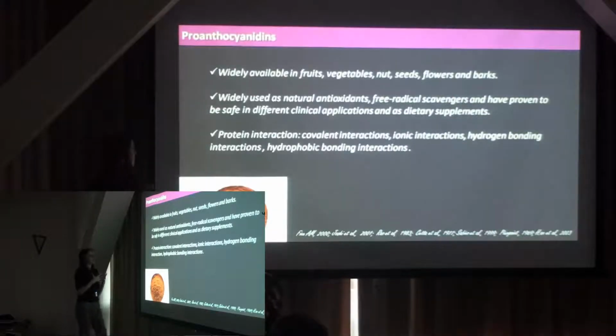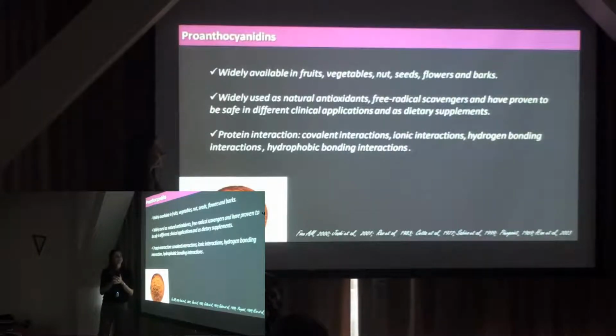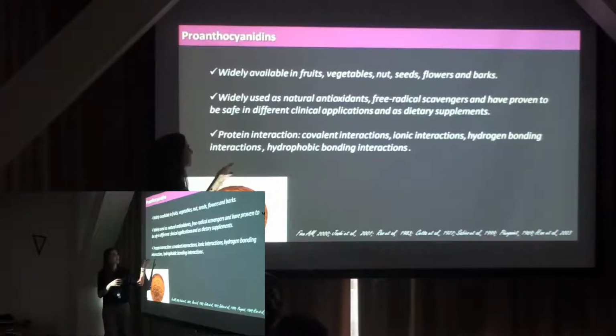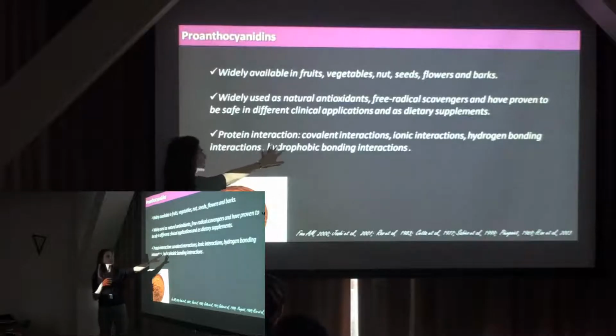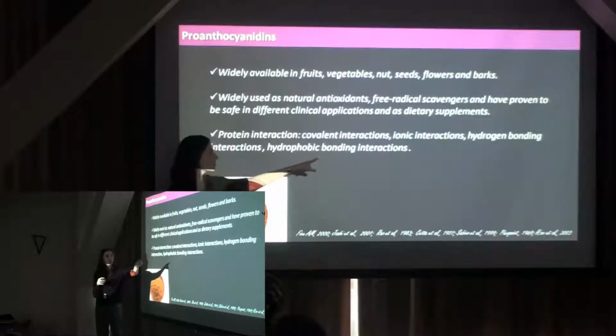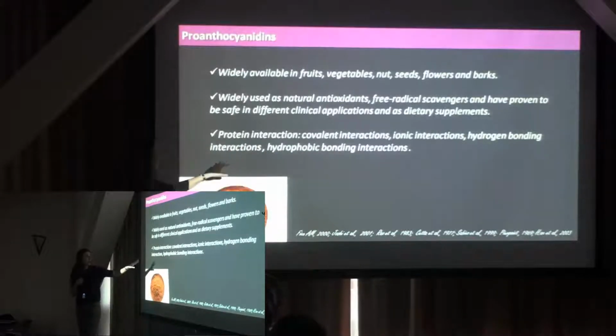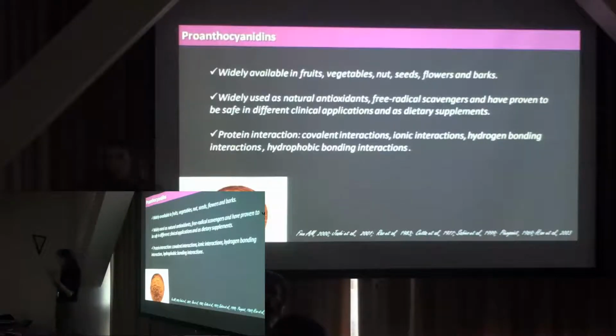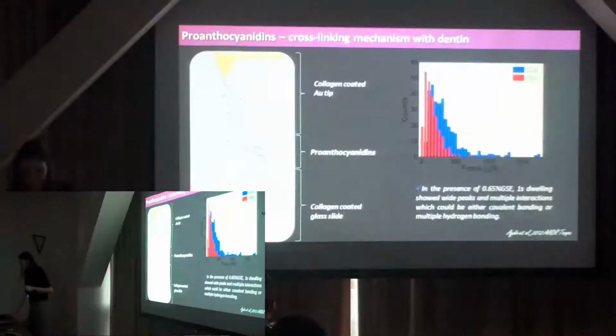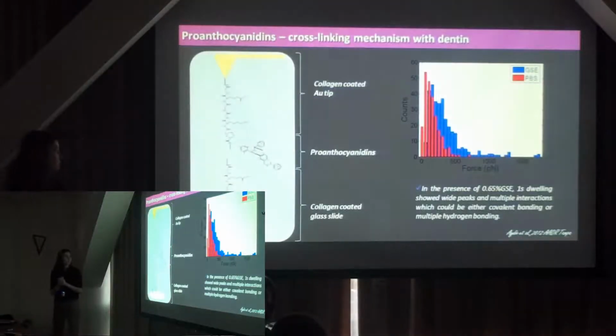And the mechanism, they bond to proline-rich proteins. The mechanisms of interaction are covalent bonds. You can also have ionic, hydrogen, and hydrophobic interactions. So a mix of things, which later on made it a lot more difficult for us to realize how hard it is to work with this material.